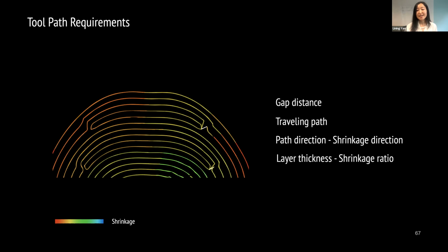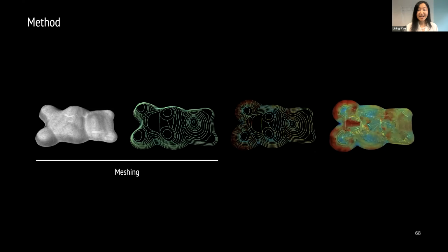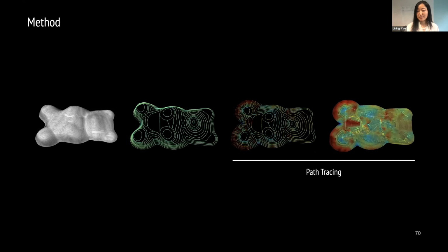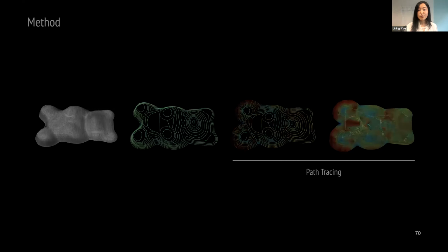For example, if you want to get a good printing quality, you actually want the line to be continuous everywhere. And also, if you don't want to leave holes, you want the distance to be as equal as possible. And also, right, there is only a limited maximum shrinkage ratio you can get for each region. So a lot of effort goes into planning the traveling path of the machine and also accommodating the limited layer shrinkage ratio. So yeah, by the end, this is what we get. Given a 3D or 2.5D shape, you can mesh it and flatten it, generate the printing trace and the G code, and you can print it out.